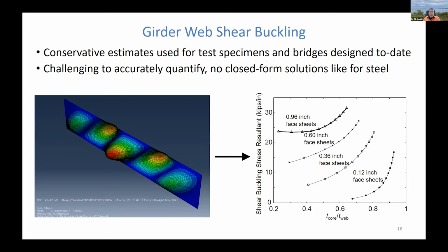So to date, we've used, again, what we believe to be conservative estimates for our specimens and the bridges that we've designed, because it's challenging to accurately quantify, and we really had to dig in. And we have been digging in over the last year or so, and we've run a very significant suite of finite element simulations. Here on the left shows the results of one of those graphically. This is the buckled shape of a foam core web panel, simply supported on all edges, subject to pure shear with an aspect ratio of about 5:1.